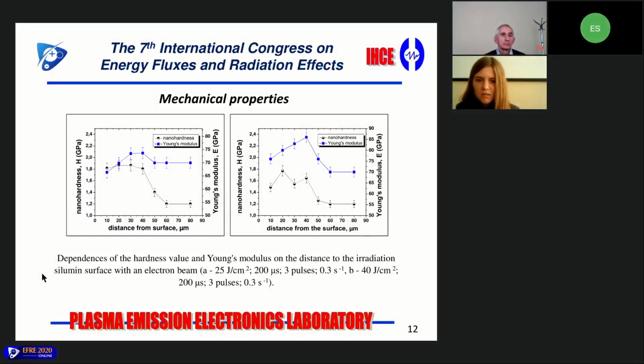It was found that the treatment of silumin is accompanied by the formation of material, the hardness of which gradually decreases with distance from the sample surface. Analyzing the result presented here, it can be noted that the maximum value of the silumin hardness is reached in an extended layer located at a depth of from 10 to 40 micrometers when the silumin is irradiated with a beam in the mode of 25 joule per square centimeter, 200 microseconds, and 3 pulses.